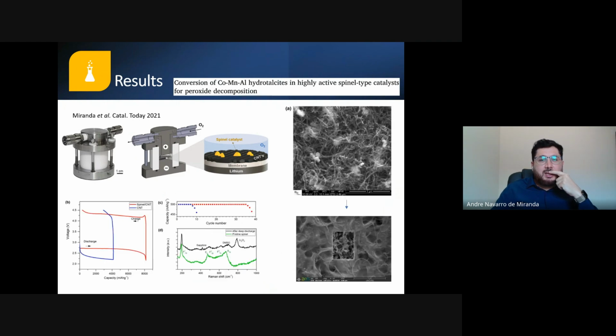So the first paper we published about this catalyst was a cell that has lithium, the membrane, and the cathode with this spinel as catalyst. So it's made of cobalt, manganese, and aluminum, as I showed you. Here you have the carbon matrix. It was a carbon formed of carbon nanotubes. And here we can see the spinel particles.